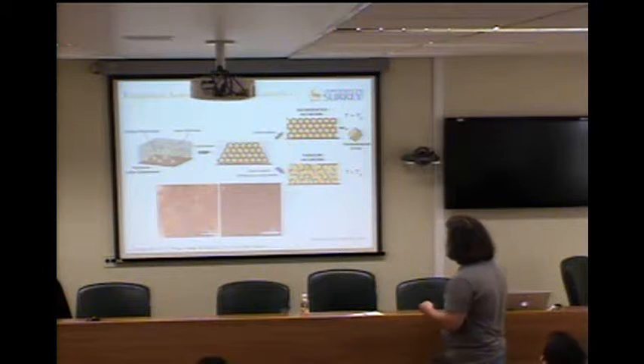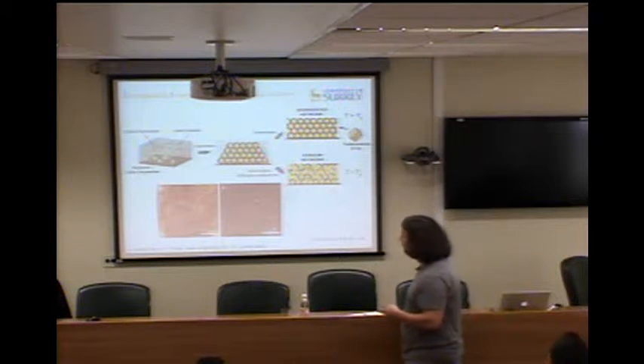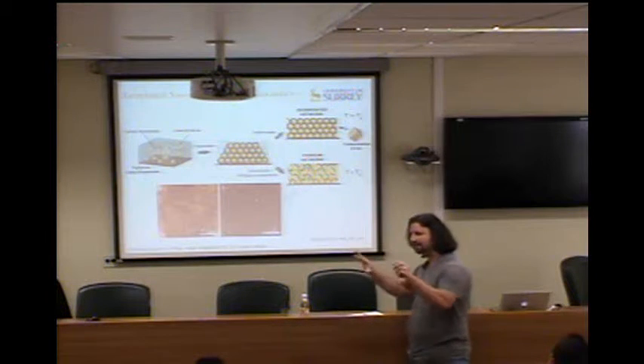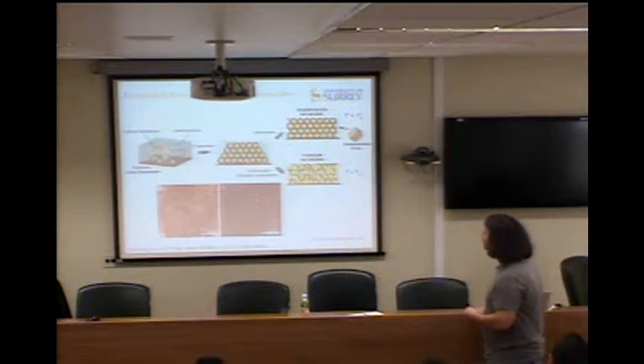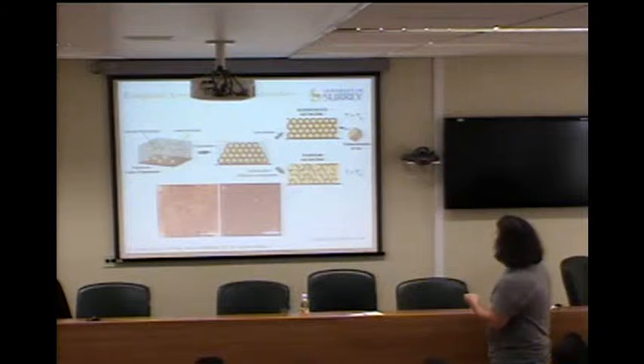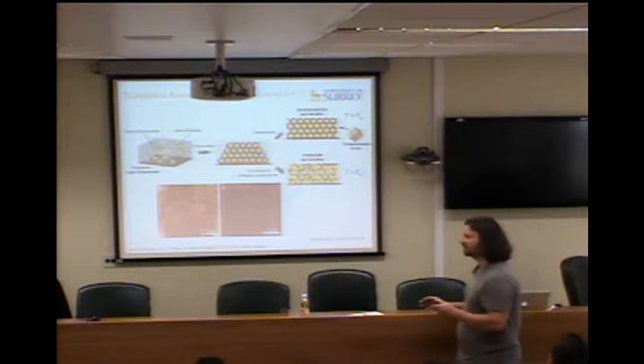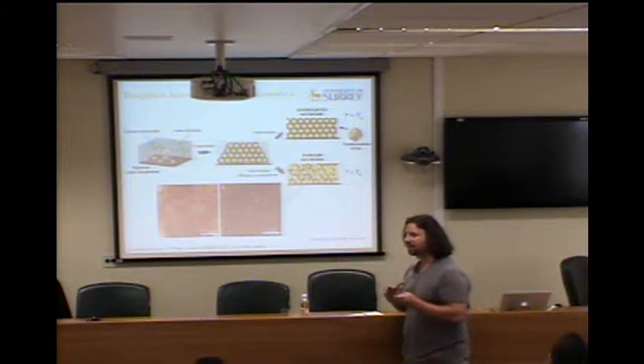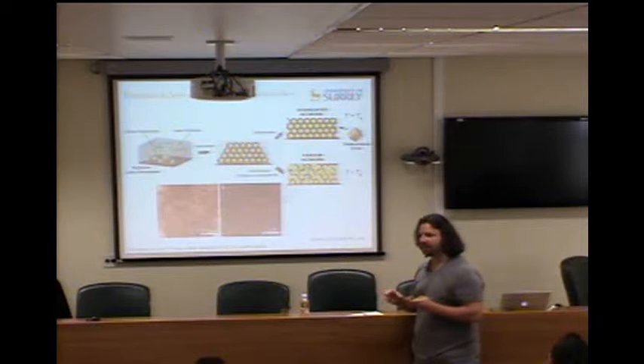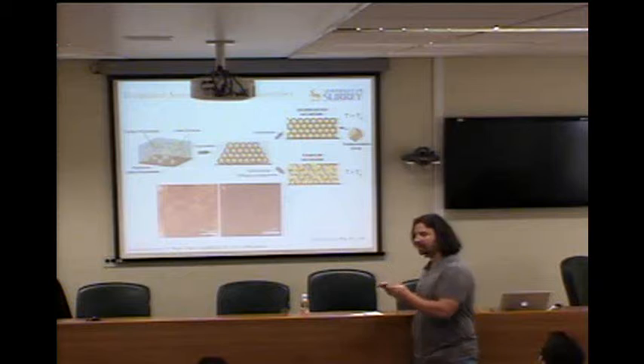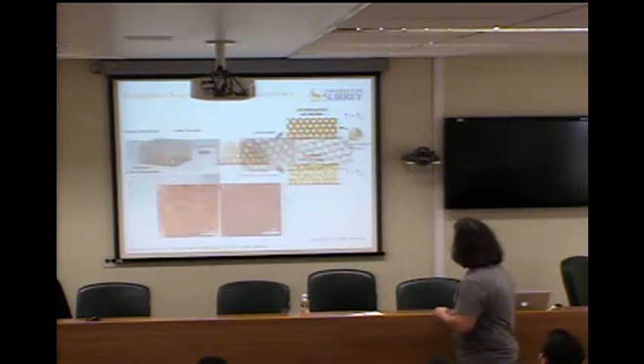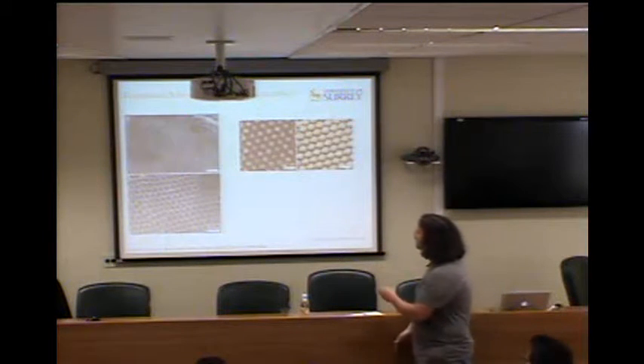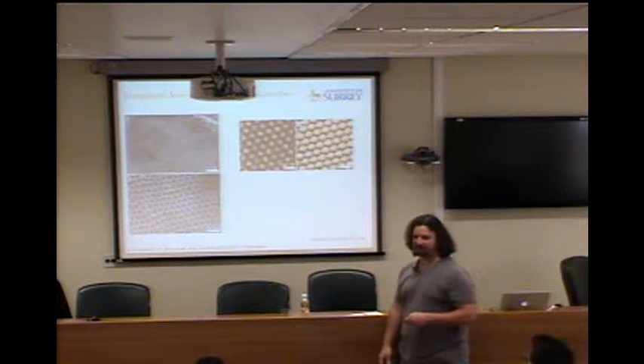If it's a very soft system, this is an atomic force micrograph image. You can see that the carbon nanotubes are isotropic, randomly arranged within the matrix. So not too interesting. But if we go to this situation, where the so-called glass transition temperature, how hard the polymer is, depends on its temperature, and this particular polymer will go from soft to hard around room temperature. Okay? So we get this amazingly beautiful self-assembly of the carbon nanotubes.